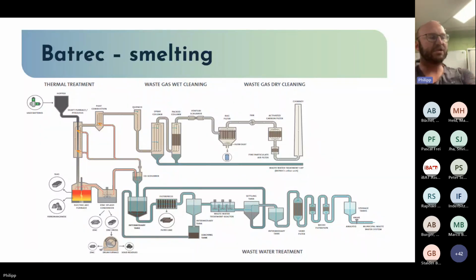So this is something special for Batrec because we are the only one who is using liquid zinc to condense this zinc from these off gas. We have a carbon monoxide atmosphere here, and this off gas is washed here, and then we can use this carbon monoxide as burning gas for our pyrolysis process and for the post-combustion chamber. So it's an internal circuit there.